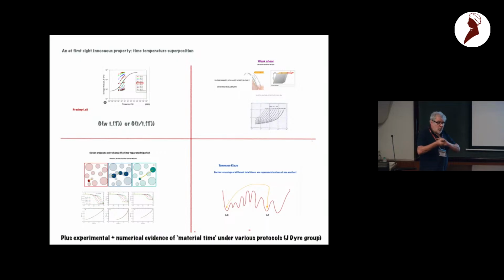It means that whatever magic this swap program is doing, it changes the shortish times, but somehow it's as if you were going through the same landscape, but with a bike instead of walking, something like that. This is in the glass? This is within the liquid as you are approaching the glass phase. Not aging. It could have been done aging, but we didn't. So it's in the liquid where everything was controlled. We were close enough to the transition so that it was interesting. We used the program at half power, only 100 times, because we wanted to compare slow with slow, and we cannot have slow and 100 times slower, so that's what we did.